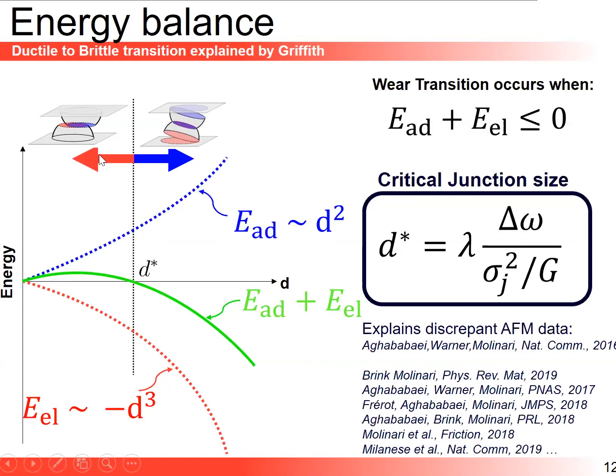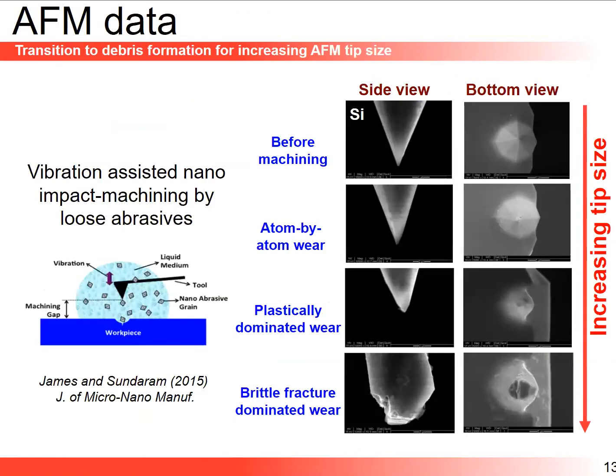That's the left here, this red arrow. To the right of D star, you can form debris. And D star is really a function of material properties. And it gives you this transition from a ductile to a brittle mode, from plastic flow to debris creation at asperities. So the simple idea has generated a lot of activity in my team, and still does. We'll give you some perspectives at the end on still open questions, and there are many.